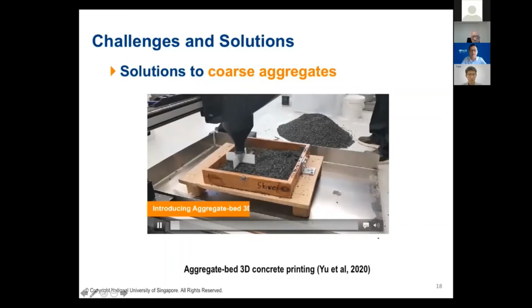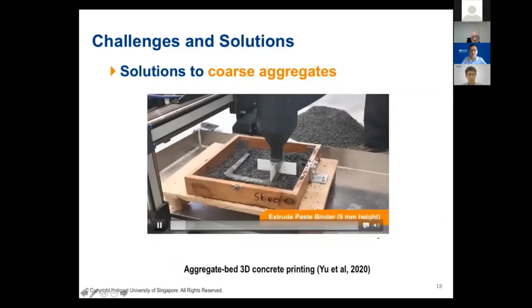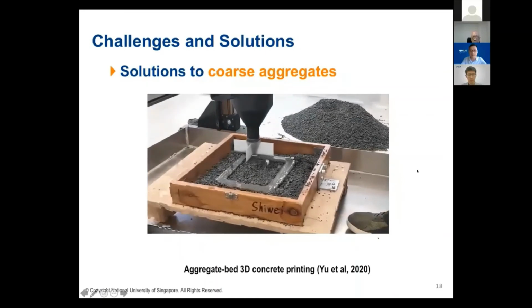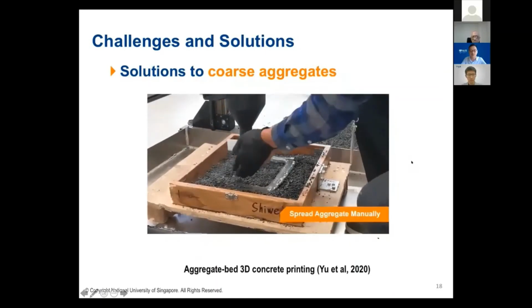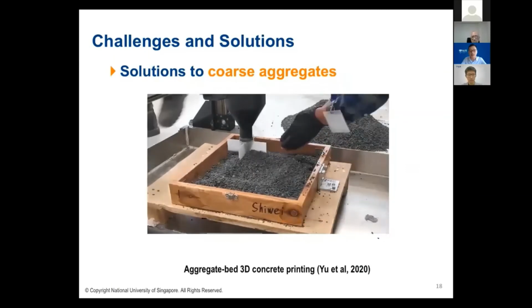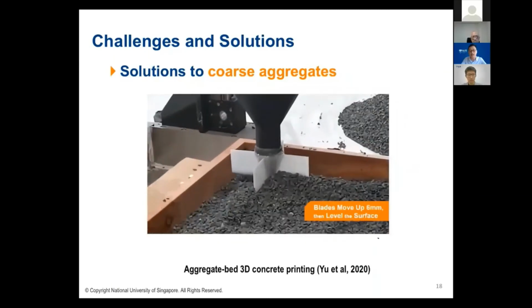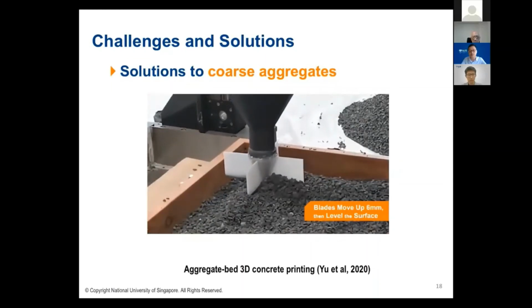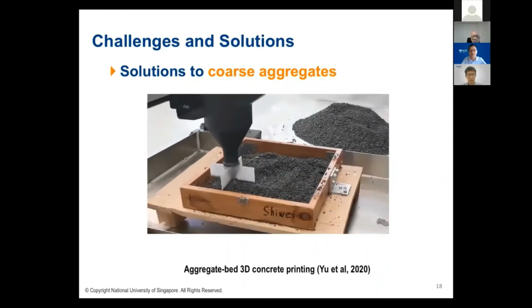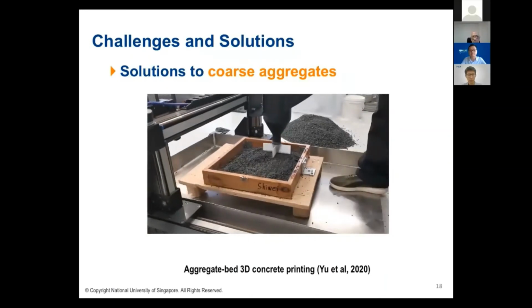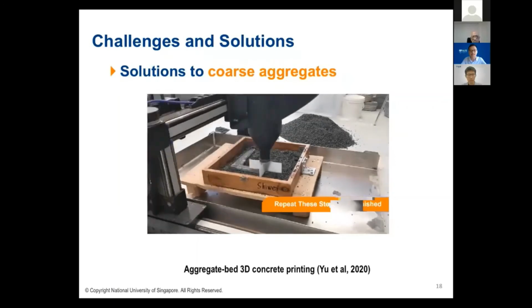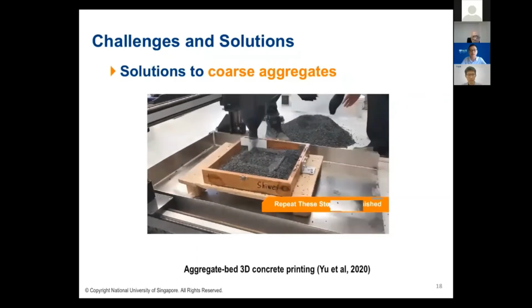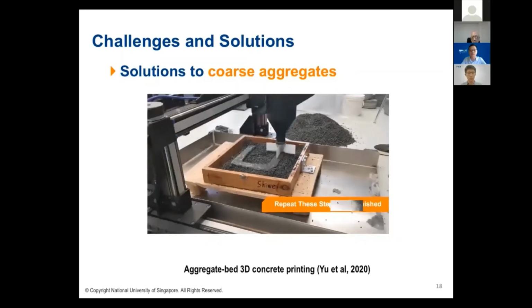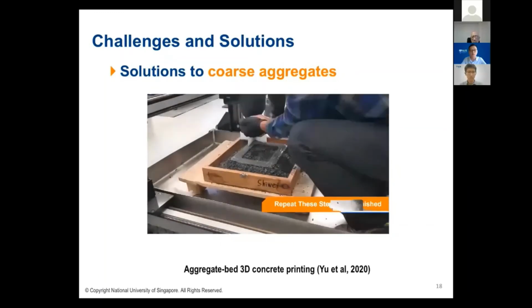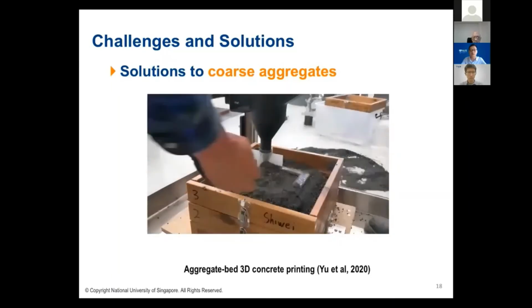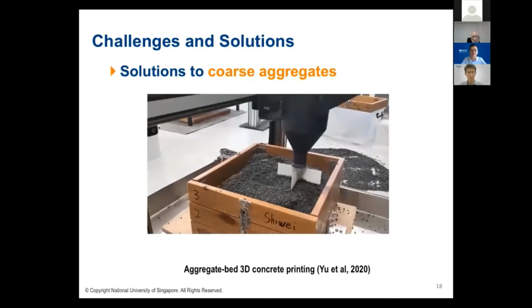So this is the aggregate bed in the box, and we print a cement paste layer so the cement paste can diffuse into the aggregate. Then we spread aggregate on top of the cement paste. Then the aggregate could be bounded by the cement paste at the bottom. Then we spread the coarse aggregate. Then we print the second layer. And then we repeat the spreading of the coarse aggregate and the printing. So we keep repeating these procedures until we realize the product we have designed.